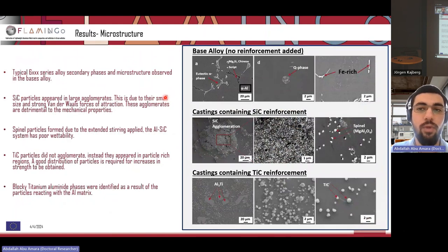These are some microstructures from the castings which we produced. In the top row, you can see the base alloy without any addition of reinforcement. In the middle row, you can see the microstructure of the castings containing silicon carbide reinforcement. And in the bottom row, you can see the microstructures of the castings containing titanium carbide. For the reference alloy, without any addition of particles, this had the typical 6000 series alloy microstructure with some of the typical phases present, such as the Mg2Si and the eutectic alpha phases, the Q phase, and of course the iron-rich phases as well.